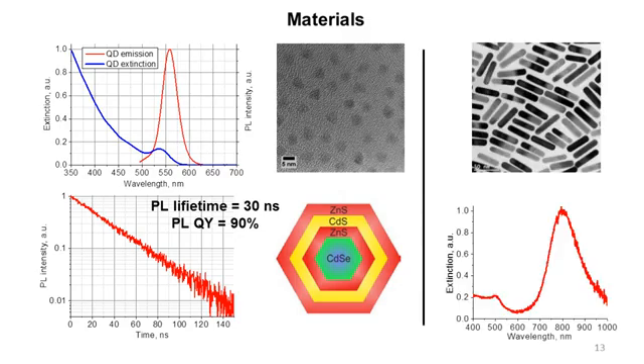They have a diameter of 12 nanometers and length of about 50 nanometers. On the graph one can see the plasmon spectrum of the gold nanorods. The longitudinal plasmon mode is positioned at the spectral maximum of 800 nanometers, which corresponds to the near-infrared transparency window of biological tissues. From the left top graph one can see that in this spectral region there are no transitions for the quantum dots absorption.